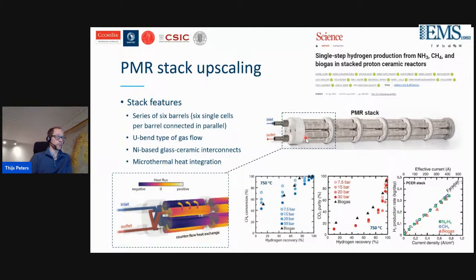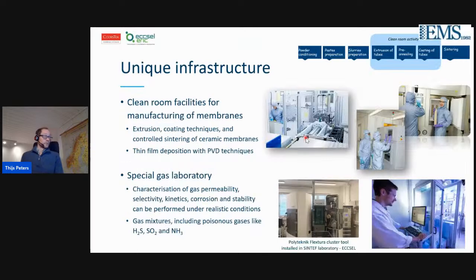This is a process that can be used both on natural gas and on biogas, and it's even being tested for the production of pure hydrogen from ammonia. For this, we have established, together with Coorstek, a unique infrastructure. So a clean room facility for the manufacturing of ceramic membranes, where the extrusion, the coating, but also the sintering, all of it is done in a clean room environment. And most of the experiments, the gas separation experiments, also in the presence of contaminants, are done in a special gas laboratory, where we can use poisonous gases like H2S, SO2, and ammonia.